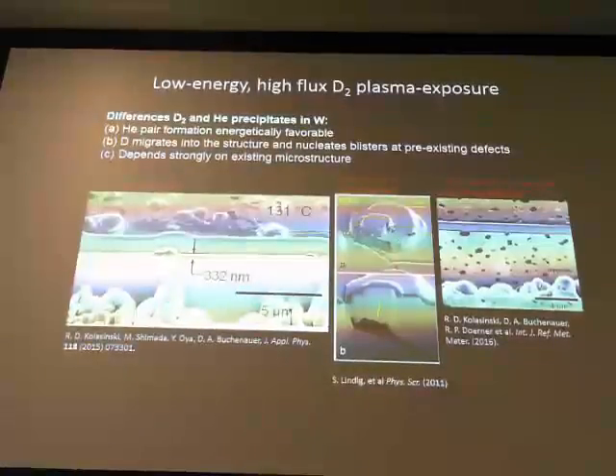And you can see this high pressure cavity that had been created as a result of this plasma exposure. And as I'll go into a little bit later in this presentation, it's absent in the case of the ultra fine grained material. So this is tungsten material with a very fine grained microstructure, where we had titanium dispersoids interspersed throughout it to pin the grain boundaries down and prevent larger grain growth.